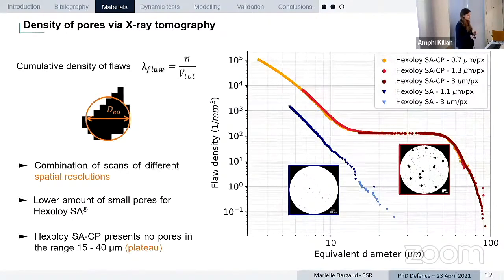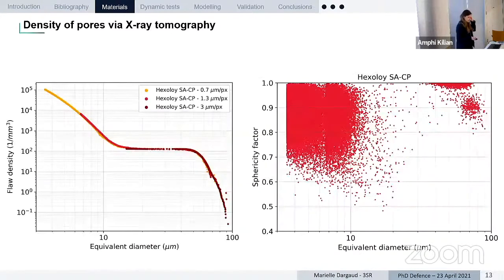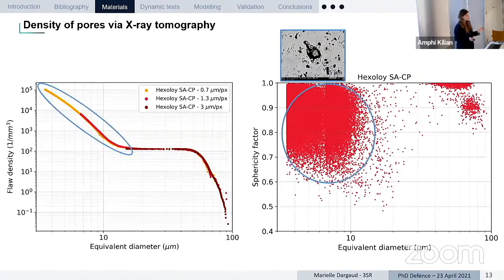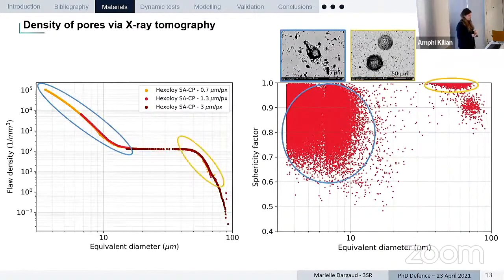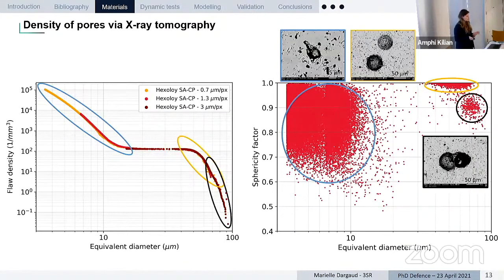So if we focus on this Hexoloy SA-CP, we can see that we have different types of pores. We have the very small ones, which mainly are sintering defects. And when we look at the sphericity factor of these defects, we can see that they're not very spherical. So we have a big cloud here. When we reach a sphericity of 1, it is a perfect sphere. For larger pores, we can see that we have pores which are extremely spherical and reach a sphericity of about 1. And then we have a last population, which is a bit less spherical, which actually corresponds to these large spherical pores, but which are touching. So they are merging, creating something a bit less spherical.